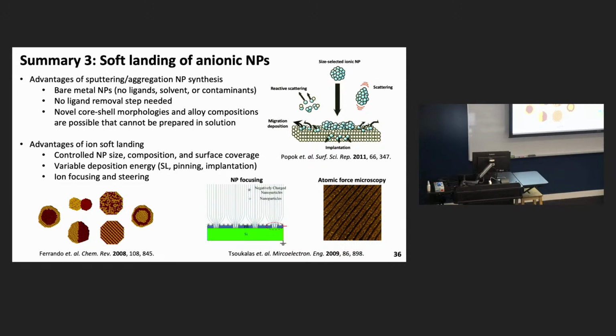And then when you combine that with ion soft landing, you can control the size, the composition, and coverage. You can vary the energy across a range from soft landing to pinning to actually implanting these materials down inside of the surface. And of course, because they're ions, you can focus and steer them, right? So you can do things like create ordered columns using masking techniques.